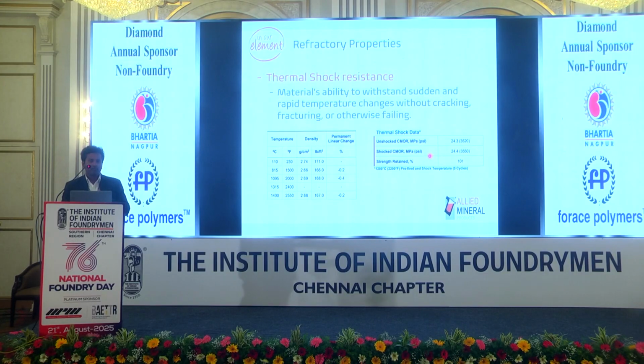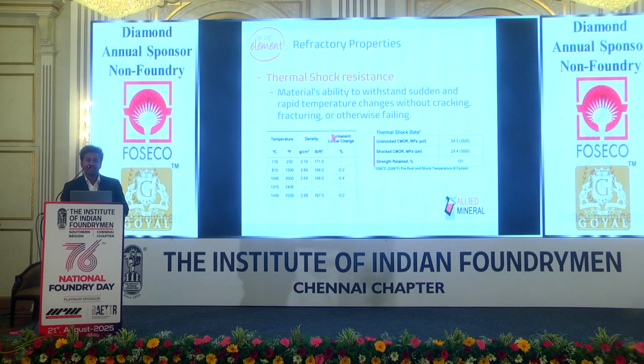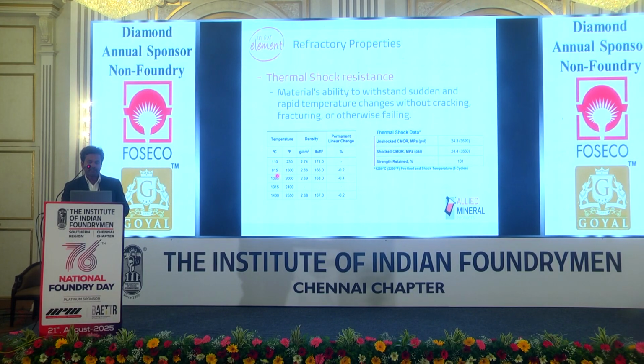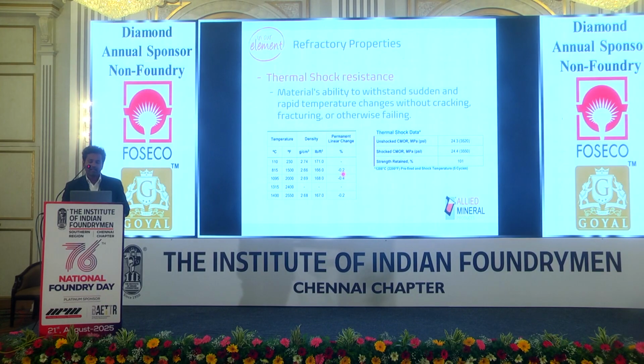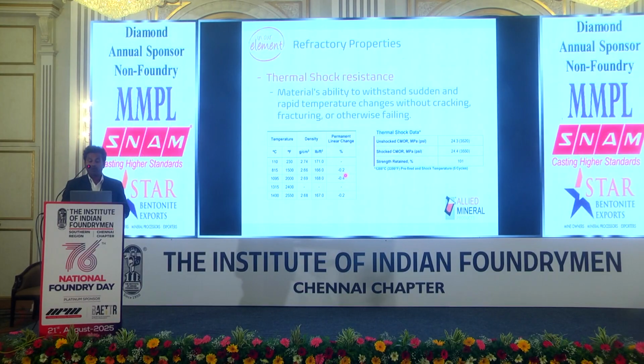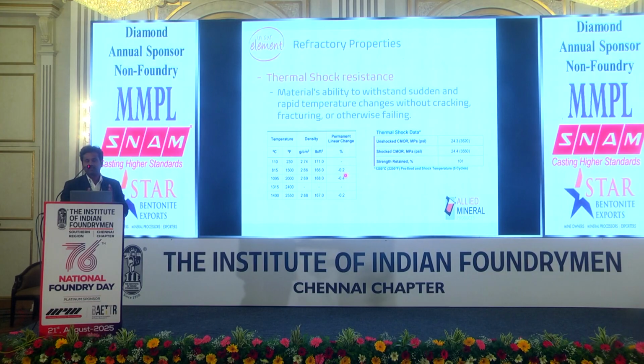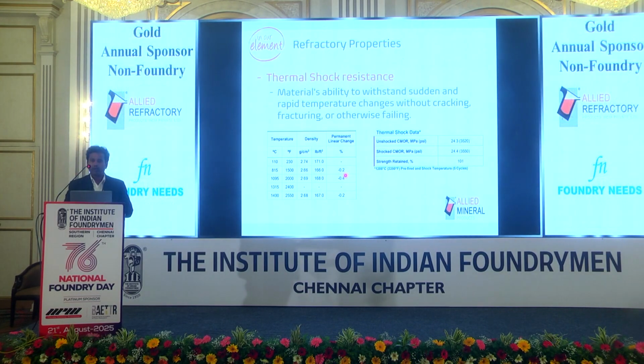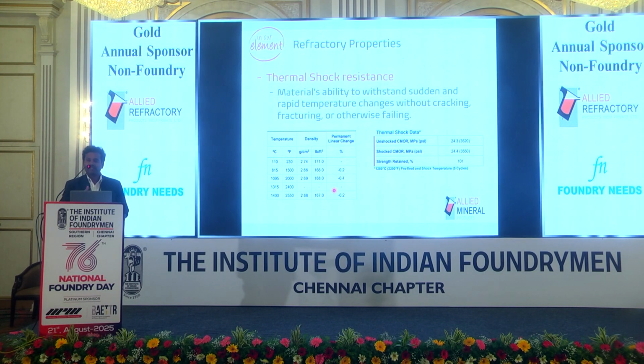Likewise, if you don't have data on thermal shock resistance, we can indirectly take it from the permanent linear change. If you see this particular product, around 815 degrees Celsius and 1095, the permanent linear change is around negative 0.2 to negative 0.4. Generally, a product is stable if the difference in the permanent linear change is less than 0.3. Here it is just less than 0.2, so this product will perform better. This is the indirect way of deriving the thermal shock resistance.